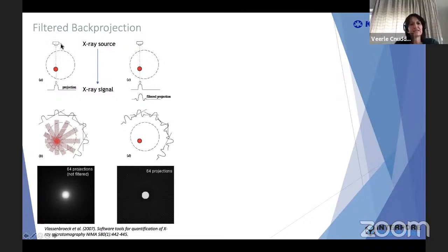If you look on the left, you see an X-ray source, the signal retrieved by the X-ray detector, and in red your sample. Your X-rays go through the sample and you get a certain signal at this location. If you do this over all the angles, you have a series of signals around your sample. Then with back projection, you back project the information, and by doing so, you are able to more or less reconstruct the original object virtually. They apply a filter in order to have sharper edges. So that is the basic principle used to come to a virtual reconstruction of the original scanned image.